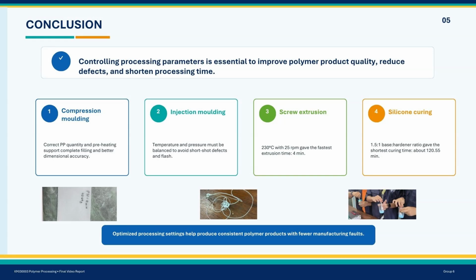For screw extrusion, the best condition is 230 with 25 rpm, which gave the faster extrusion time of 4 minutes. For silicone curing, the 1.5:1 base to hardener ratio gave the shortest curing time, about 120. Overall, optimized processing settings can produce more consistent polymer products with fewer manufacturing faults.